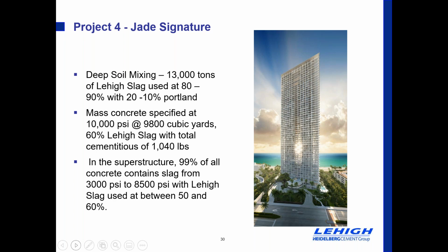Then once that was completed, mass concrete then was put into the hole that was dug after the deep soil mixing, and that was mass concrete at 10,000 psi, where we used 60% slag, total cementitious of 1,040 pounds. What we're seeing in southern Florida is that because slag is widely available now, most of the mass concretes are moving towards slag for temperature control, but they can also achieve higher strength.